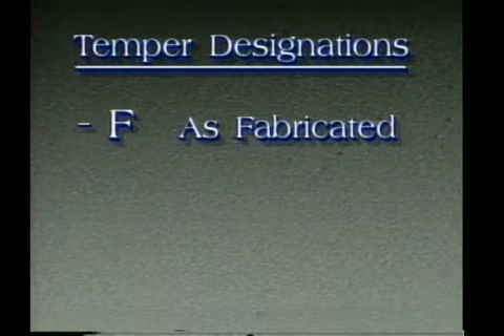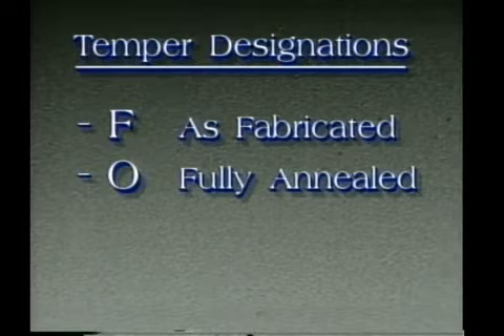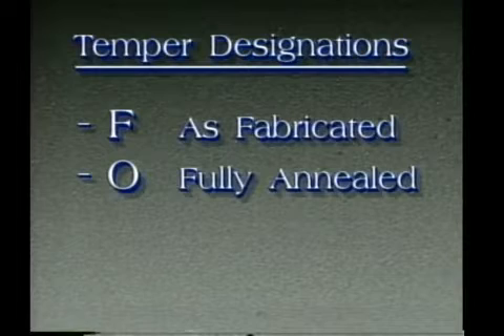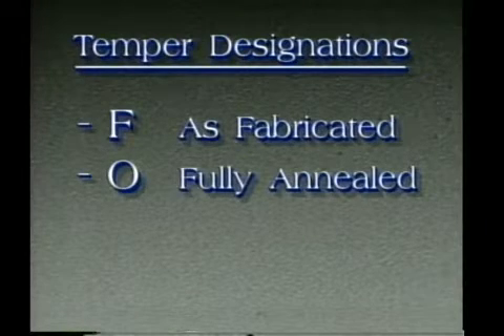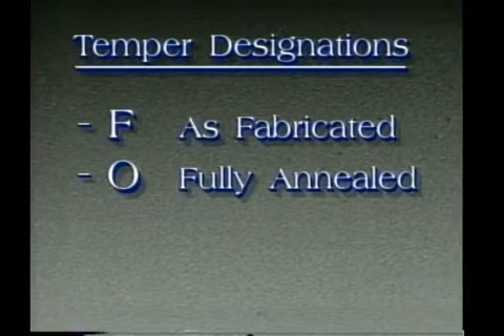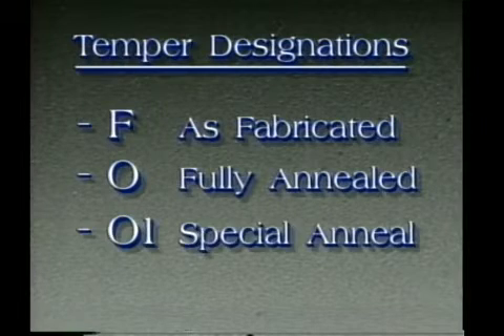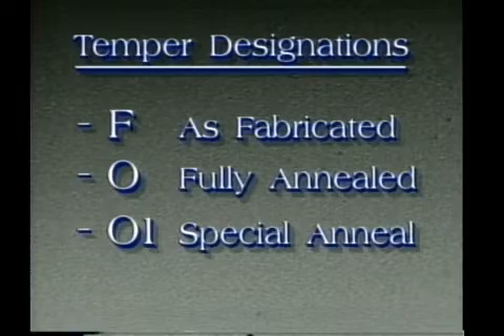In addition to T designations that identify the final heat-treated condition, there are other temper designations that the heat treater must recognize. These are designations that are used for interim processing operations prior to the final hardening treatment. Prior to the heat treatment, the material is usually received at the heat treat plant in a non-hardened condition. These are as follows. F, the temper used to designate material in the as-fabricated condition, usually from the producing mill, such as forged, as extruded, and so forth. O, the O designation represents the fully annealed or softened condition. Material is placed in the annealed condition so that it can be further formed or fabricated in some manner, or to relieve stresses placed in the material by some fabrication process. O1 is a special formability anneal used for machining applications.